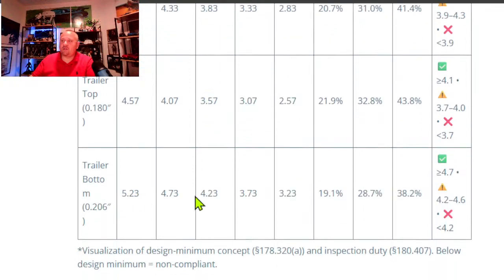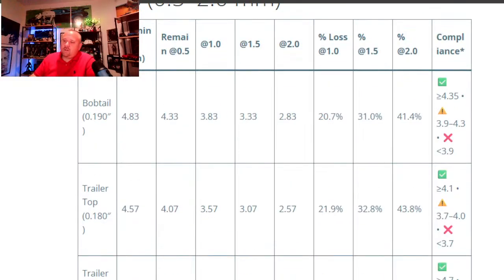Same thing when it comes to the bottom of the trailer. Looking at these numbers, starting nominal is 5.23. Anything under 4.2 millimeters thickness is out of compliance. This is the bottom of the tank. You have a remaining thickness of 4.73, and if you remove 1 millimeter, you're left with 4.23. That already removes 19.1%. Anything more than that, 1.5 millimeters to 2 millimeters of material removal, you're out of compliance.